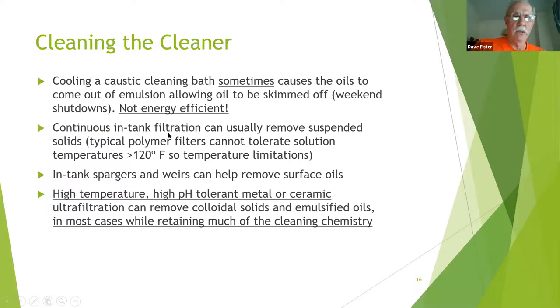You can do continuous in-tank filtration that can usually remove suspended solids. So you're talking particulate. Now, the bad news is typical polymer filters can't tolerate solution temperatures above roughly 120 degrees Fahrenheit. So a polymer filter has limitations. And I always recommend bullet three, to have in-tank spargers and weirs to at least get the surface oil removed.